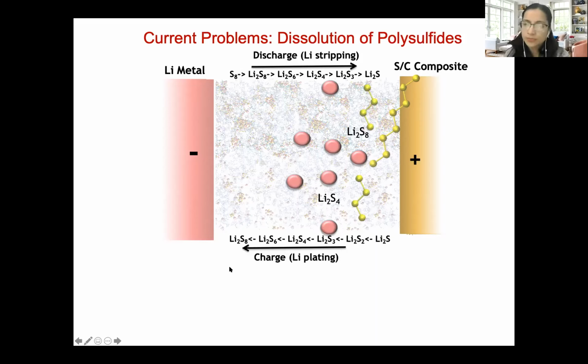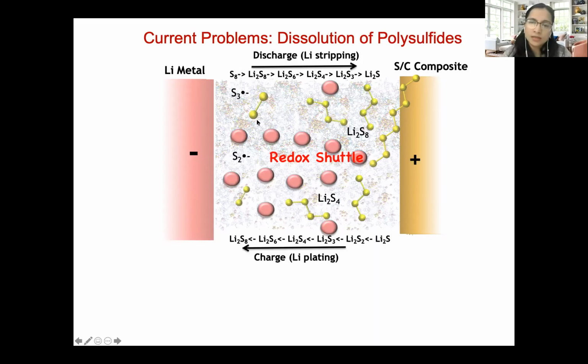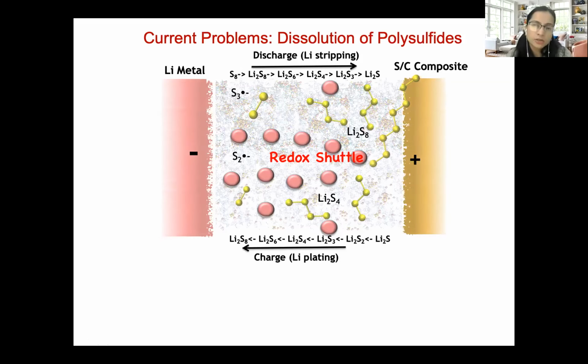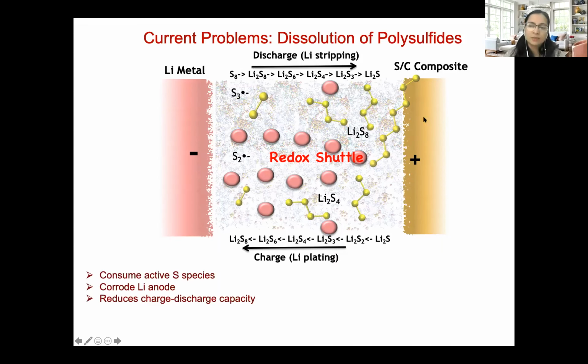So far, so good. Nothing's wrong with these batteries. The problem arises when a lot of these lithium polysulfide species, along with some radical anions, start migrating toward the lithium metal side, and they result in parasitic reaction at the interface and in the electrolyte, which is called the redox shuttle phenomenon. And this process takes place every time we are charging the battery. So we ultimately end up consuming the active sulfur species, and we are also corroding the lithium metal anode, which reduces the charge discharge capacity.